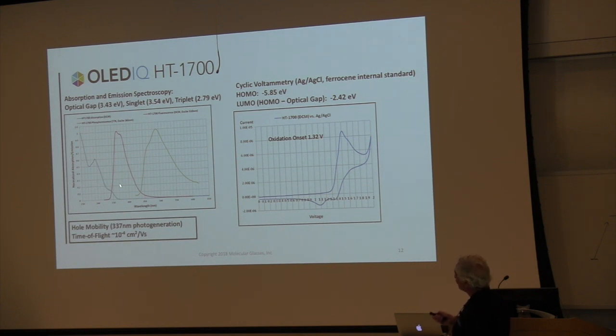Others use 1/3 of the way up as a single energy. They're all different. The other thing you have to do is you want to measure the cyclic voltammetry with respect to an internal standard. We use ferrocene, but there's no universal standard for what ferrocene is with respect to vacuum. So we have to modify these numbers depending on the company we're talking to.